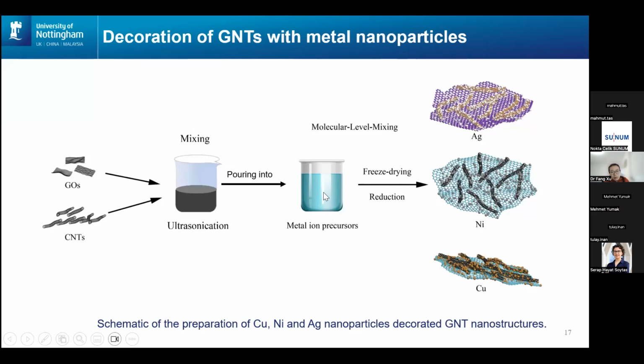So we just dissolve the salt into water and we pour our well-dispersed graphene oxide and carbon nanotube into the precursor, okay? And then we mix the two dispersions, the two solvents, using magnetic stirring. After they are well mixed together, we put it into liquid nitrogen to freeze them, and then use our freeze dryer to dry it. After that, we will get metal salt mixed with our carbon nanotube and graphene structure. It should be a 3D structure.